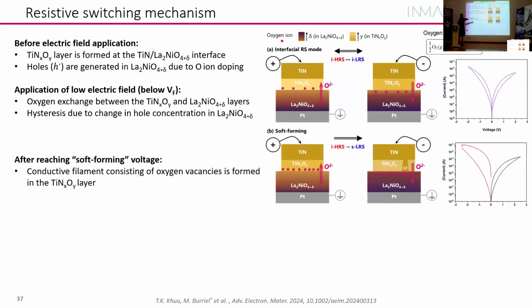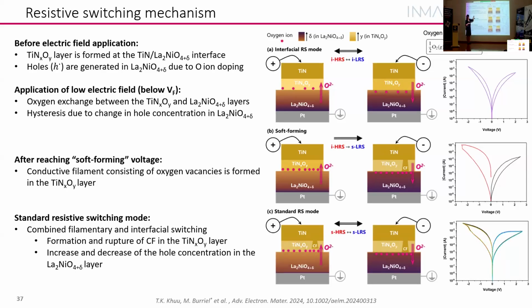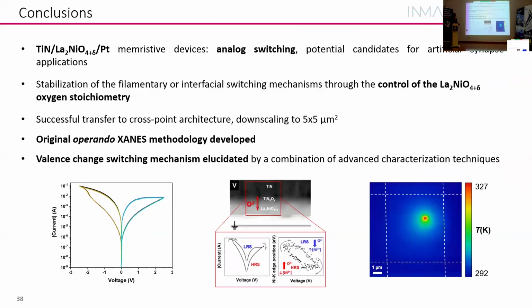When we go to the forming, what happens? We believe that there's a conductive filament forming in the titanium oxynitride layer. And then when we do the switching, this filament would be connecting and disconnecting. So we have in reality a behavior that is not only filamentary, not only interfacial, because we have in the whole surface oxygen that is going in and out between these 2 layers, but at the same time, there's a conductive filament that is connecting and disconnecting. And with this, I would like to pass to the conclusions.